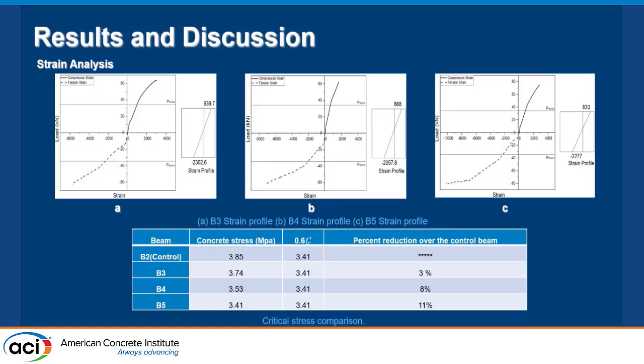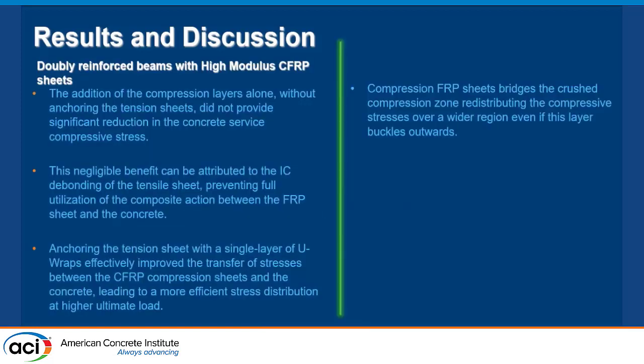And then for B3, while we're adding more sheet on the compression side and anchoring, we are going from 3.85 to 3.74, like 3% less. And B4, we are getting 8% less. And B5, we are getting 11% less. We are exactly matching the limit. And so we are getting a more ductile behavior while we are using the compression sheet and the U-wrap anchoring.